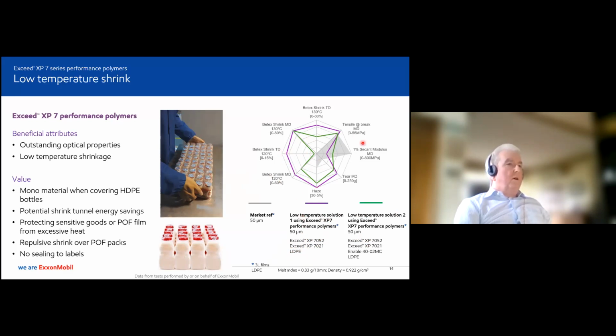Now, it will be a softer resin, which is why the secant modulus is quite soft, but there is always a trade-off between trying to get down to these very low shrink temperatures and then the modulus of that film structure. So if you need a slightly higher modulus, then you can incorporate some Enable, for example, or a good medium density grade of resin that has shrinking properties.